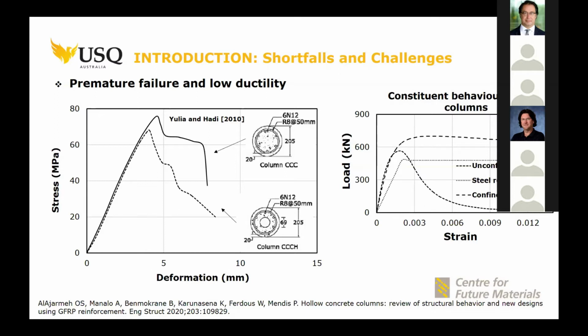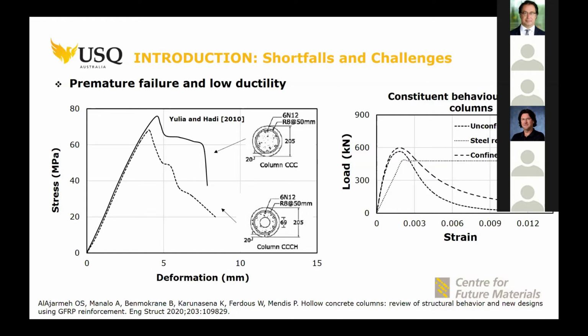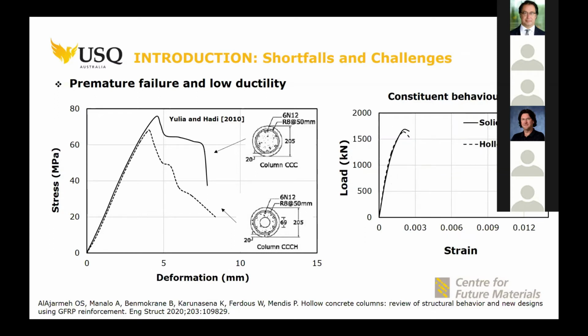However, the confined core inside is the major difference between hollow and solid columns. You can tell from here the steel bars again and the unconfined concrete are similar. However, the confined concrete is different. That is due to the absence of the core inside, which changed the stress formation inside the core from triaxial in the solid section to biaxial in the hollow section. And the brief enhancement in the confined core is related to the lateral reinforcement. By knowing all of these things, you can tell from the figure on the right-hand side that it closely matches the experimental figure on the left-hand side, so we now know what is happening in the hollow concrete columns with the steel bars.